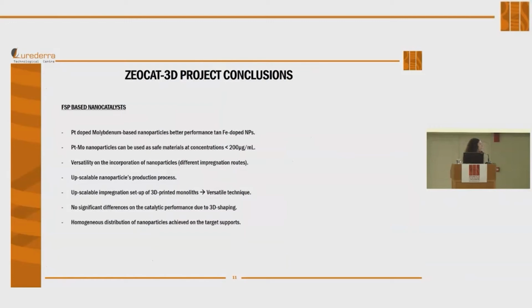Okay, I would like now to take the chance to sum up all these highlights in some relevant conclusions, to basically highlight the advantages of these nanocatalysts that are synthesized through the FSP equipment based technique. As I mentioned, we can work and design a wide range of nanoparticles, so we can fit different requirements. In this case, we finally ended up selecting the platinum molybdenum because of its better catalytic performance compared to the iron.